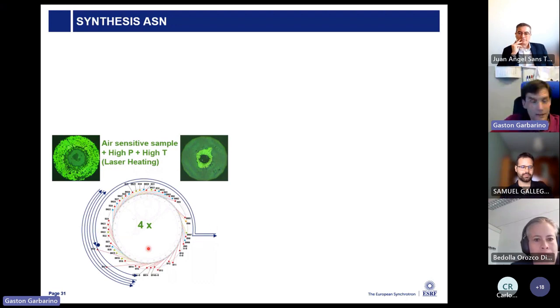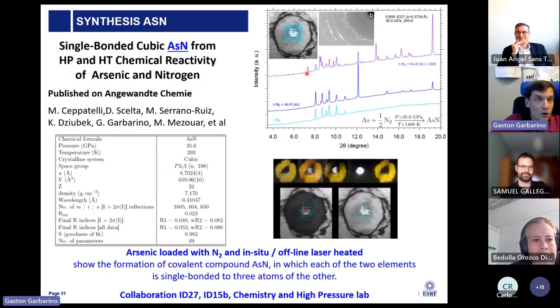And this was during COVID, so we were alone here on the ring. It was a little bit of fun, but again these samples were quite inhomogeneous due to the laser heating synthesis, and we were able to solve the structure and get a new single-bonded cubic arsenic nitride synthesized at high pressure and high temperature using laser heating on ID15B. This is an example in which the collaboration between the beamlines and with the different support labs allows us to have successful experiments.